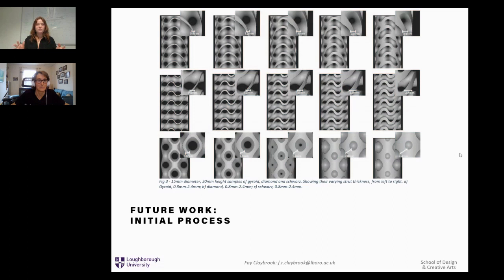So overall, there was the 5 different porosities for 90A TPU and 3 porosities for 60A TPU. And the 2 different materials with 7 replications each, which equals 105 samples for the 90A and 63 samples for the 60A TPU. And the current information I can tell you is the overall characteristics of these samples acted the same as the Schwarz P, where the higher the porosity, the reduction in compressive modulus and the maximum compressive modulus, which you would expect from the previous study and the design of them.